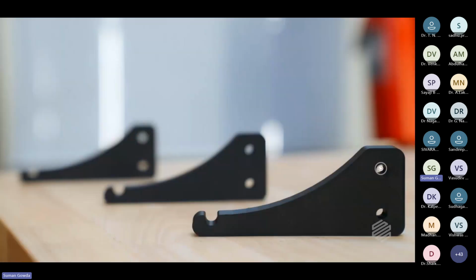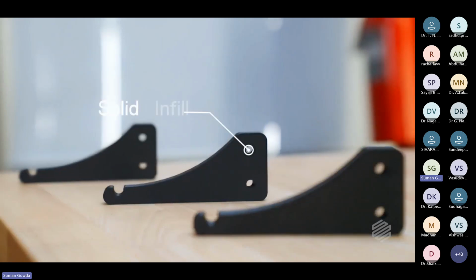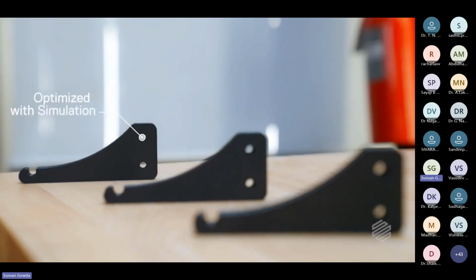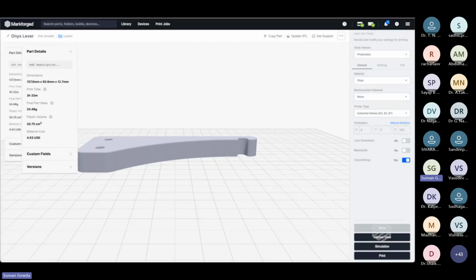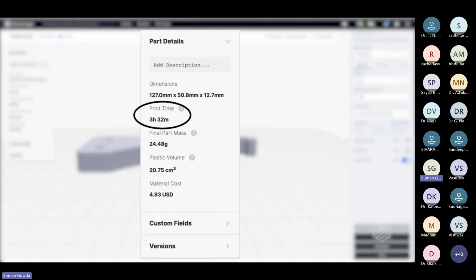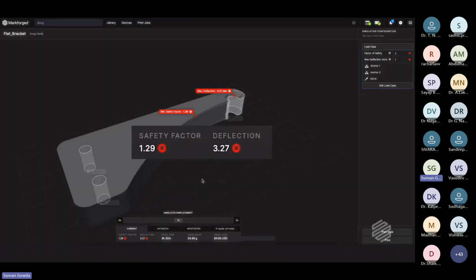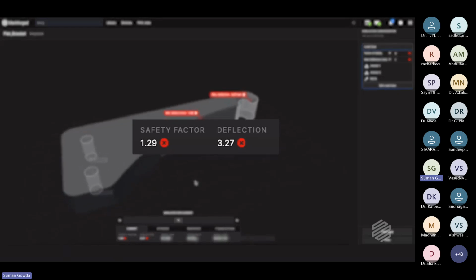Let's look at 3 different variants of the lever. The first was printed with default slicer settings. The second with a solid infill. The third part is optimized using simulation. We can see in Eiger that the first part took 3 hours and 32 minutes to print. It's not strong or stiff enough for us to use.